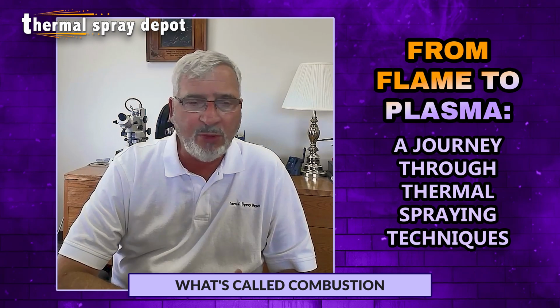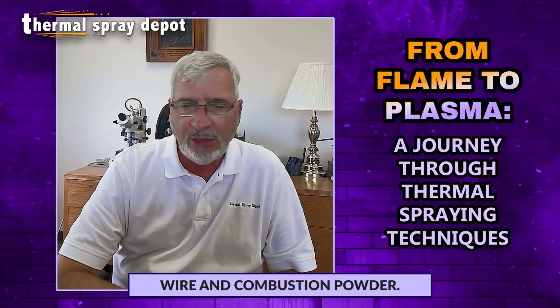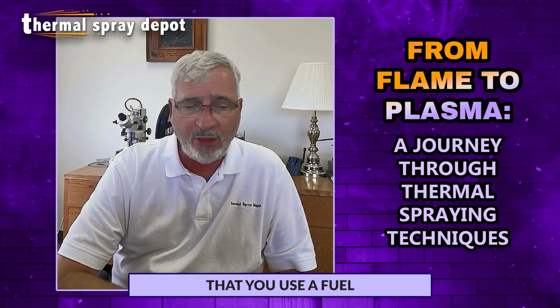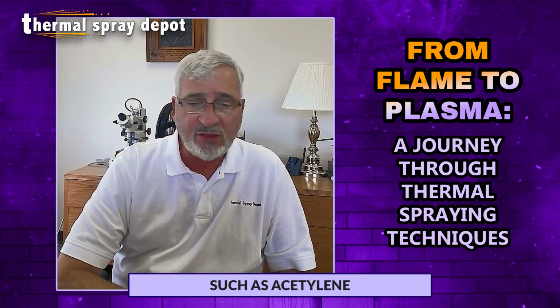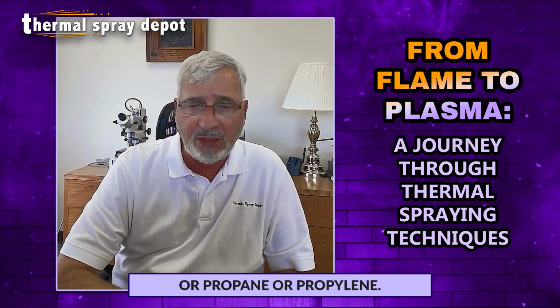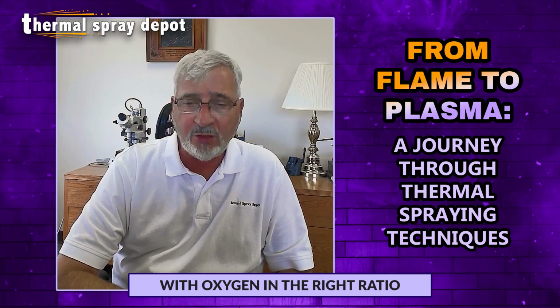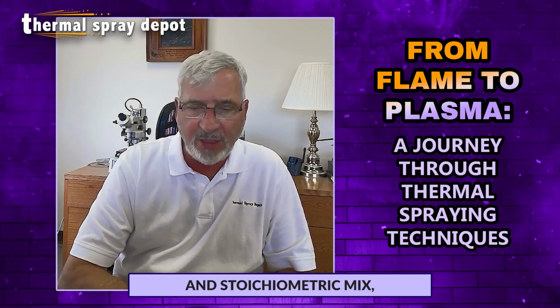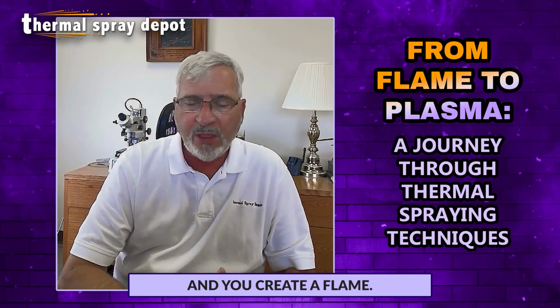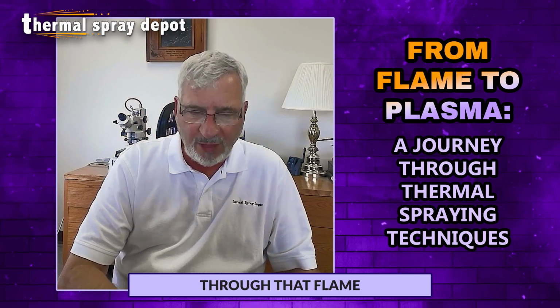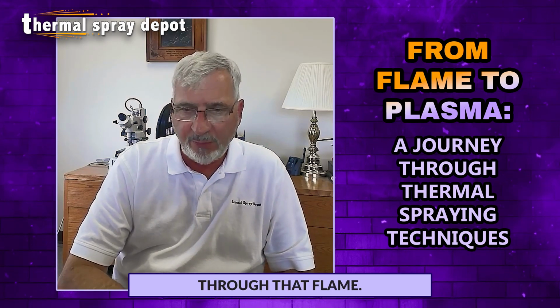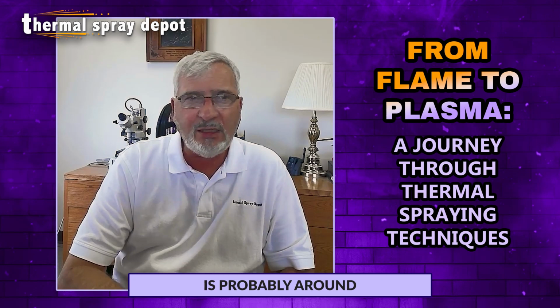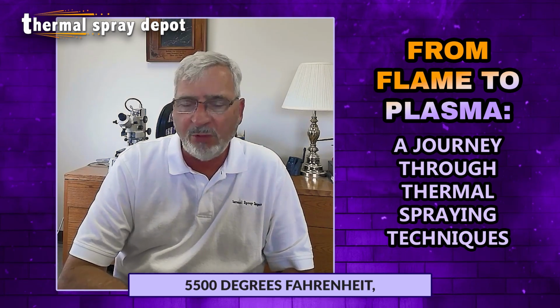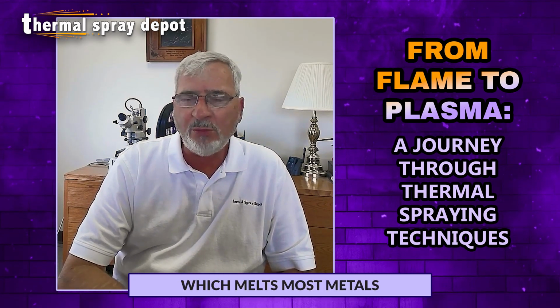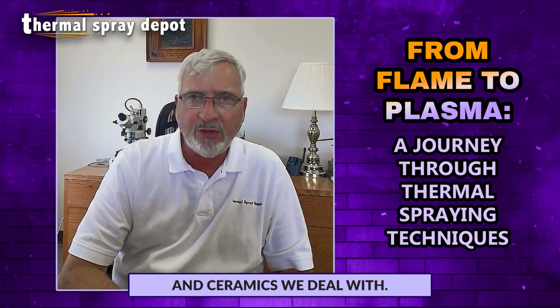You have what's called combustion wire and combustion powder. That's where you use a torch with a fuel such as acetylene or propane or propylene. You mix that with oxygen in the right ratio, the stoichiometric mix, and you create a flame. Then you feed a wire or powder through that flame. The flame for acetylene is probably around 5,500 degrees Fahrenheit, which melts most metals and ceramics we deal with.